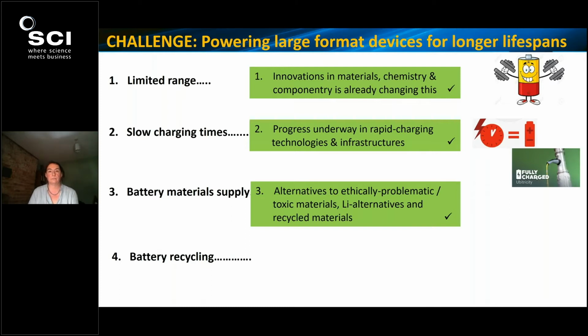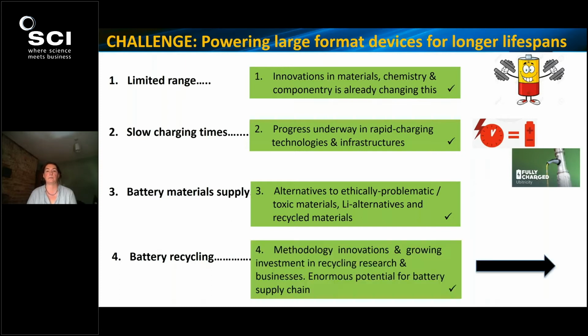One of the initial cathode materials contains a lot of cobalt, and there have been a lot of concerns about the ethical issues surrounding these materials, including their toxicity. And so alternatives are being used for this. For example, higher nickel cathodes are making great progress, both in research and commercially. There are alternatives to lithium-ion technologies such as sodium-ion, and of course, compared with using virgin materials for manufacturing, we are seeing a lot more investment in recycling, both in methodology and innovations.